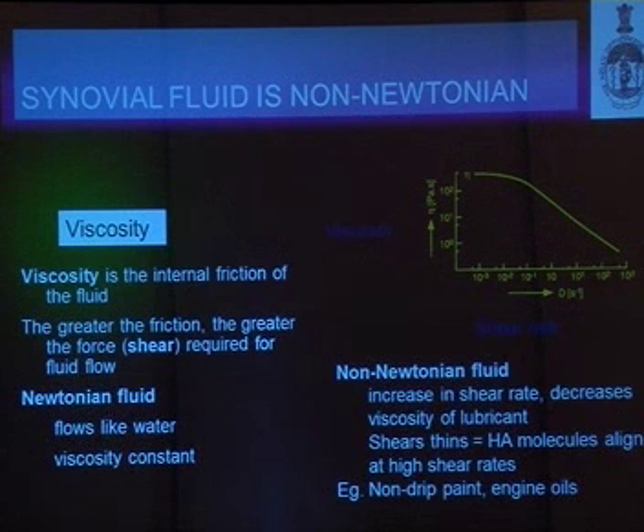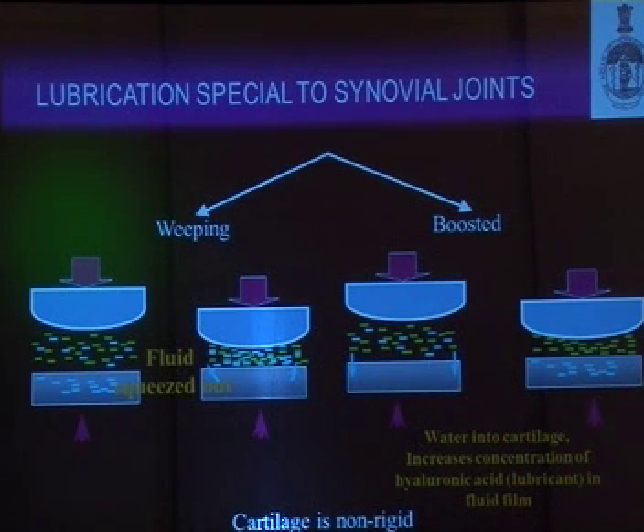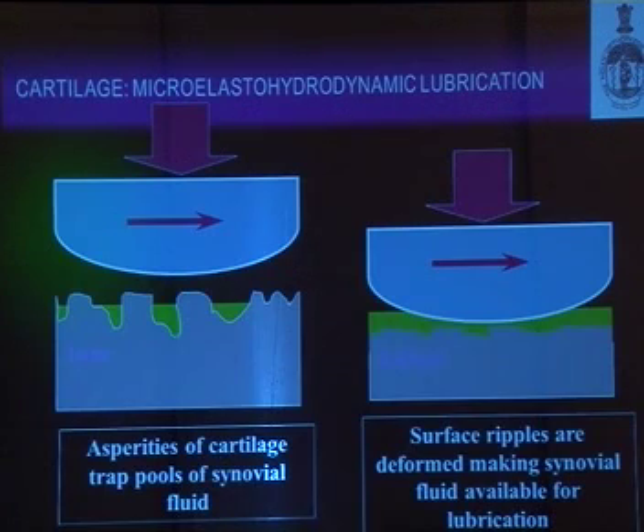We know the synovial fluid is non-Newtonian. It has a viscosity, which is the internal friction of the fluid, quite similar to the surface friction. The greater the friction, the greater the forces required for the fluid flow. The lubrication is special to the synovial joints. I'm sure you've read about weeping and boosted lubrication during your master examinations. And the cartilage has a micro elasto-hydrodynamic lubrication, normally for very small asperities of 0.05 to 1 micrometer.